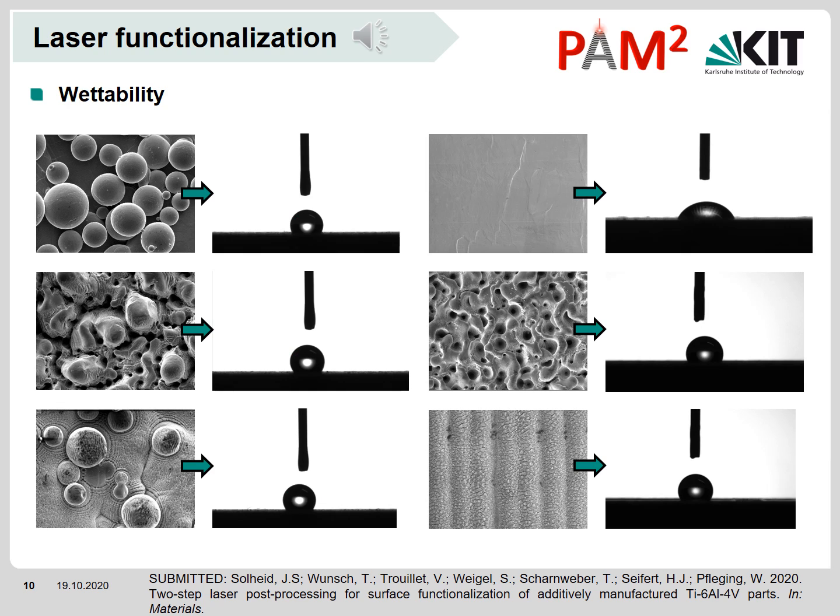The functionality of the parts was initially evaluated through a wettability analysis. We could observe that distinct topographies obtained from varied steps of the process chain can present similar wetting behavior. These behaviors also differed from what was expected for rough and smooth surfaces in some cases, which confirmed that the surface topography alone cannot dictate the wetting behavior of the parts.